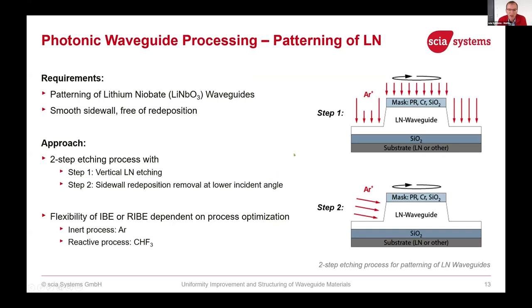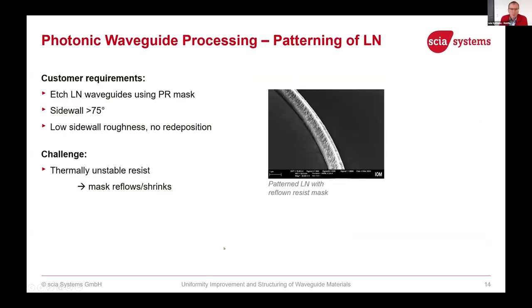So, of course, in different times. The first step is a long etching process, while the second one is just a short cleaning flash. And we apply there a mix of noble gas and reactive gas. So we apply there typically the reactive ion beam etching process flow with CHF3 as a reactive process gas. Here are some examples of what can be achieved or what can happen. We see here a waveguide that should be structured through a photoresist mask with a requirement of larger than 75-degree sidewall angle, of course with low sidewall roughness and no redeposition.